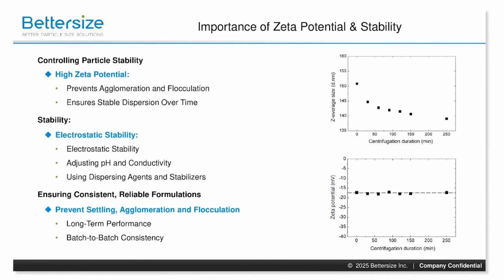So what is the importance of zeta potential? Having high zeta potential controls particle stability. High zeta potential, either positive or negative, creates strong electrostatic repulsion between the particles. This repulsion avoids clumping and aggregation and prevents particles from coming together, forming a stable suspension. Maintaining the high zeta potential ensures that particles remain evenly dispersed in the medium, preventing them from settling. It maintains that uniformity.